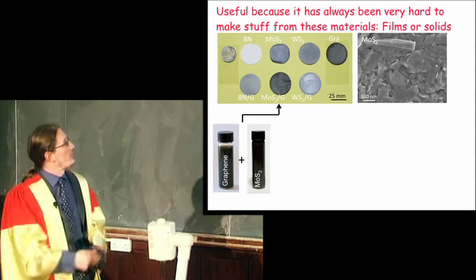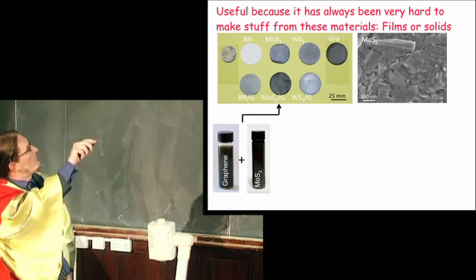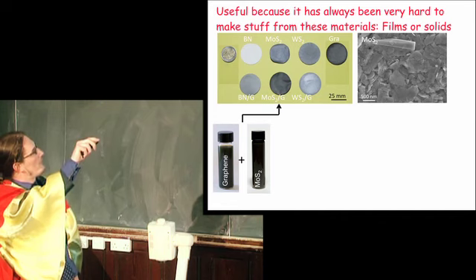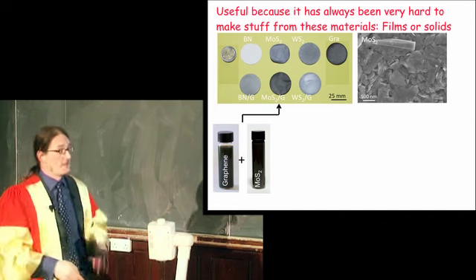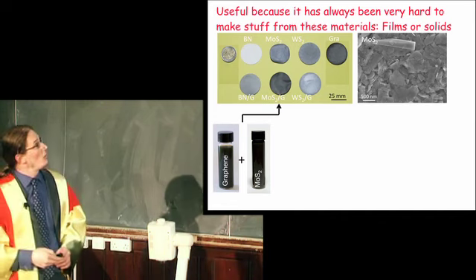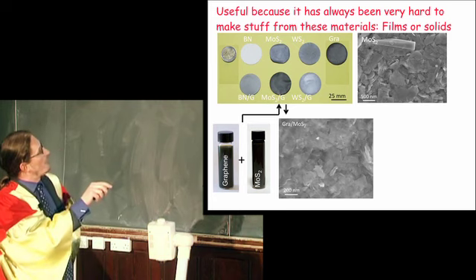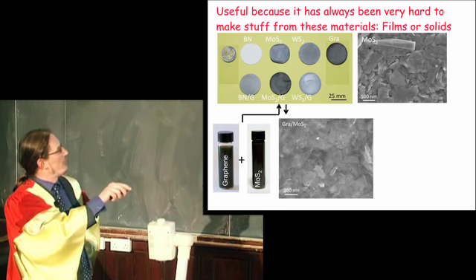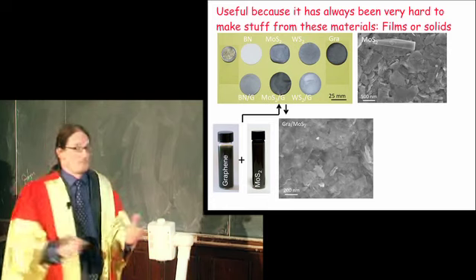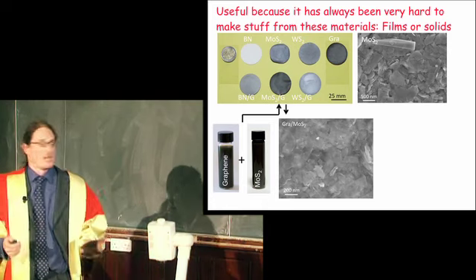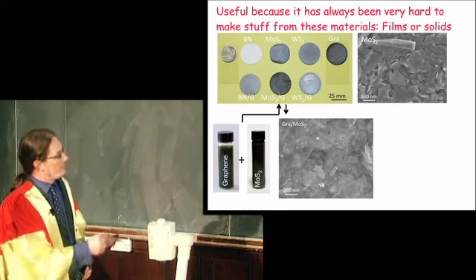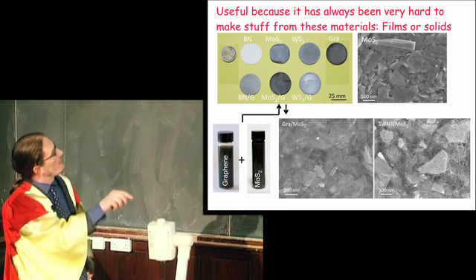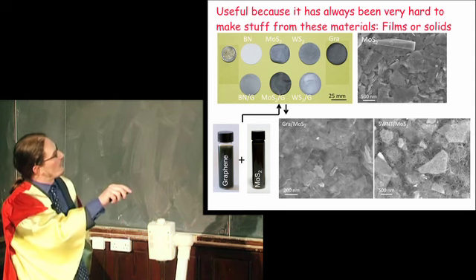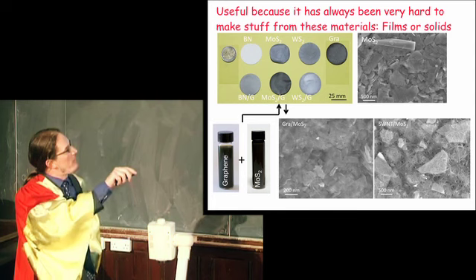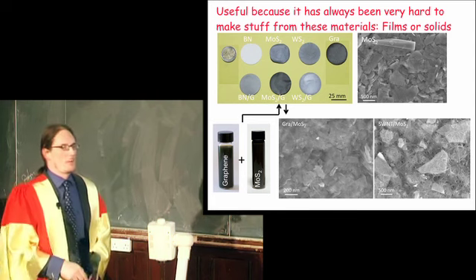You can then make composite films, which are, in this case, 50% boron nitride, 50% graphene, 50% molybdenum disulfide, 50% graphene, etc. And if you look with the electron microscope, you'll see that for the graphene molybdenum disulfide composite, it's just an array of sheets because the two components are just platelets. But if you do the same thing and make a composite with single-walled nanotubes and molybdenum disulfide, you'll see the flakes are embedded in a matrix of carbon nanotubes.